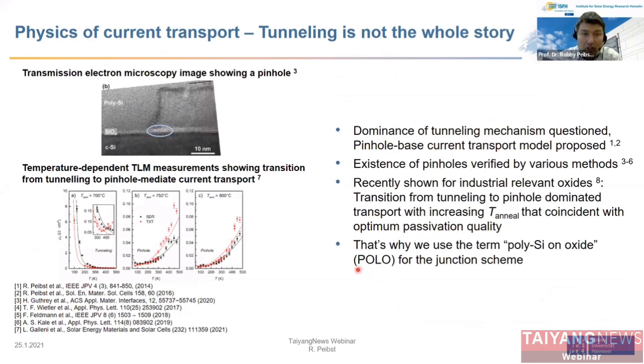And one fundamental aspect is the physics of the current transport mechanism, which in the name TOPCon, as suggested, is the quantum mechanical tunneling through this interfacial oxide between the polysilicon and the crystalline silicon, which you can see here in this TEM image. But already some years ago, we questioned whether this is the whole story, and it turns out it is not. There are also some pinholes formed in the interfacial oxide, which also contribute significantly to the current transport mechanism.